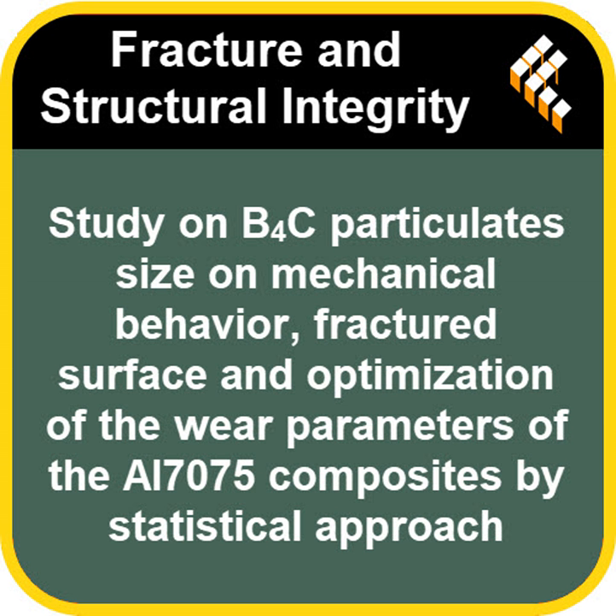But here's where the study had some results that seem, well, backwards, for these specific composites anyway. What did they find about sliding speed and distance affecting wear? Yeah, this was really interesting and, like you said, counterintuitive. They found that better wear resistance, meaning less wear, was achieved at higher sliding speeds. Higher speed, less wear. Usually you'd think faster means more friction, more heat, more wear. You would. That's the typical behavior for many materials. But for this specific AL7075 B4C system, the results suggested something else is happening. It might be related to specific changes in strain rate sensitivity or friction heating effects at the interface that actually make it more resistant at higher speeds. It's quite specific to this material combination. So the fact that higher speeds can sometimes reduce wear here, that's potentially huge for designing high-speed parts, isn't it? Maybe you don't always have to trade speed for durability. Exactly. It really challenges the conventional thinking for this system.